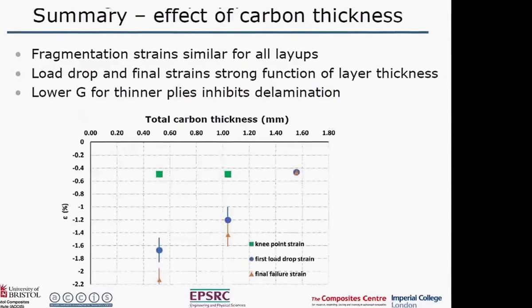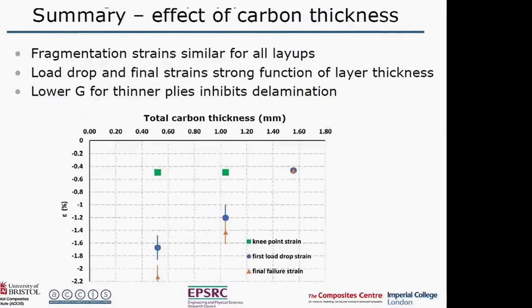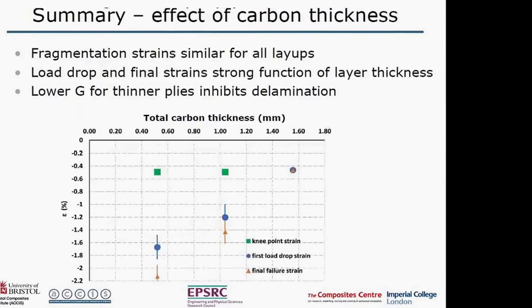So we can summarize those results on this plot here, which is showing the strains as a function of the total carbon thickness. So this is single, double, and triple blocks of carbon all the way through the thickness. And you can see that the fragmentation strain is pretty constant, but the strain for delamination and for final failure is increasing substantially with the reduction in thickness of the carbon plies.